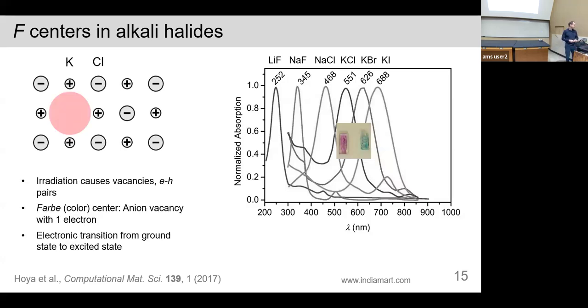If you irradiate this, let's say with electrons, you can damage the crystal. You can knock out a chlorine atom, creating a vacancy. And you create lots of electron-hole pairs because the X-ray has lots of energy. So the color center is a vacancy, like a chlorine vacancy, with one electron inside. And that acts a little bit like an electron in a well. And, as you know, you can excite an electron from the ground state to an excited state. And so that's what we're seeing here. The electronic excitation from the ground state to some excited state gives us a peak.